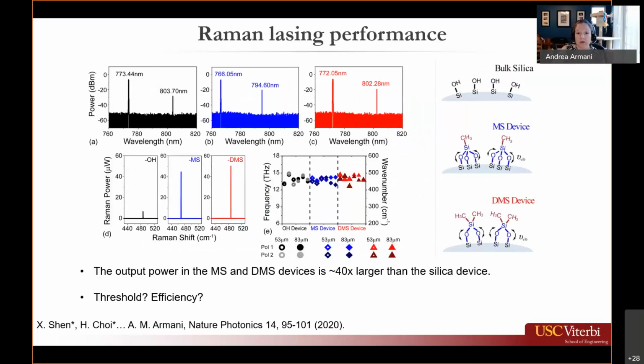Then we looked at the Raman lasing performance. All the subsequent measurements were done at 765. The first 3 spectra on this slide show the Raman lasing measurements of first a silica device, then a methyl silane-coated device, then a dimethyl silane-coated device. When plotting in dBm, it's not immediately obvious that there's an improvement in emission intensity for the methyl-coated and dimethyl-coated devices. So then we plotted it with power as opposed to dBm on the y-axis.